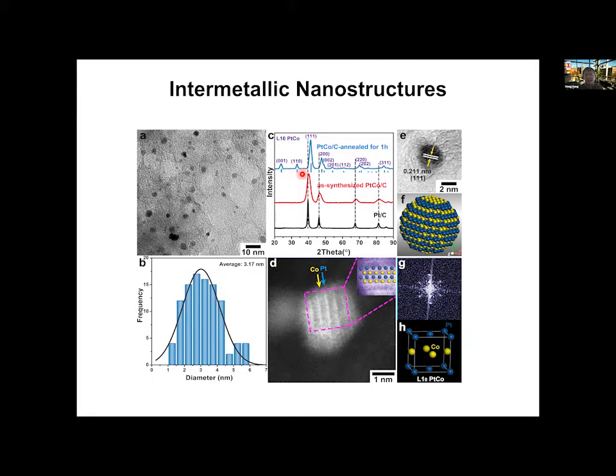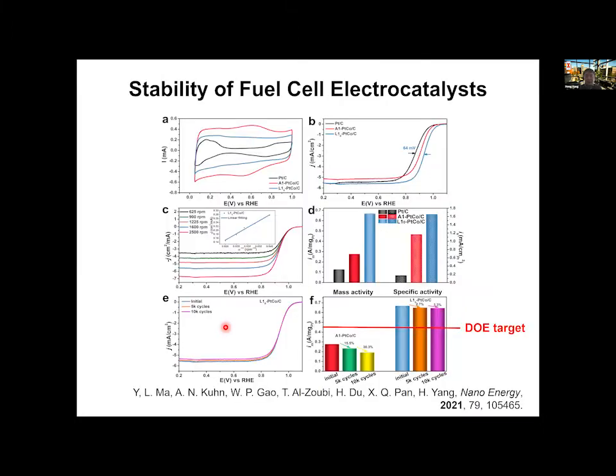and the density, the internal particle size, primarily reach about 3 nanometers also. So this is the idea that we try to promote the formation of intermetallic nanoparticles on the substrate at ultrafine structures. Previously, the smallest one for the platinum cobalt reported was somewhere between 5 to 7 nanometers. We hope that we'll be able to push this further and see whether we can increase the density by changing the substrate further.